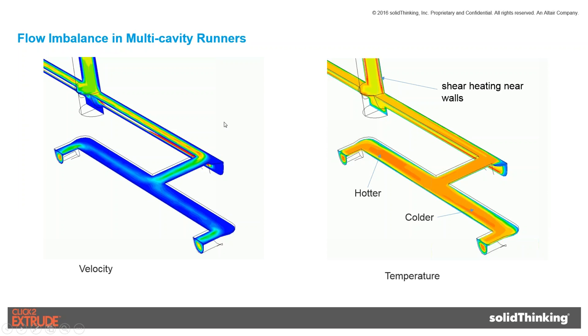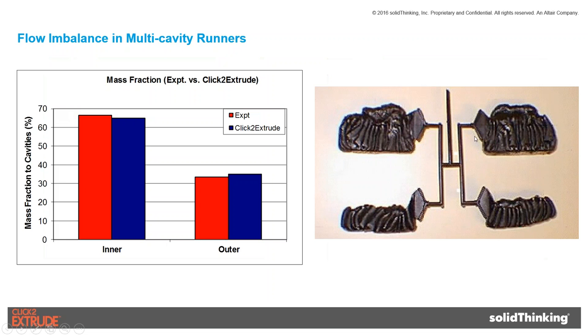So here I'm showing how the polymer is flowing through the runner system and how the shear heating is happening near the wall, and as it is flowing through, where the colder and hotter material is flowing. Since this is a little bit hotter compared to this region, we see more polymer getting filled on the top one compared to the bottom one. And this was compared with the experimental data. We compared how much material is flowing through all these four exits of this injection runner system, and that compared very well with experimental data.